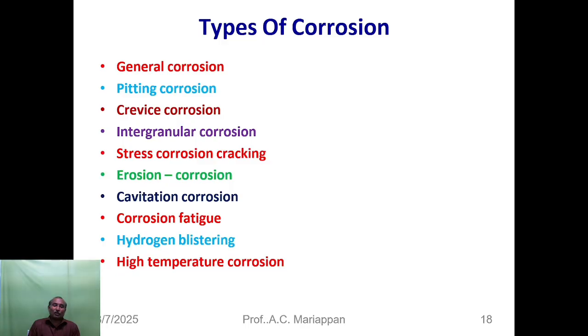The blister, the metal will be blistered inside the surface; it will not occur outside, it will occur inside of the equipment on the surface of the wall. By visual inspection, metal blistering can be observed. If you break the blisters, two nearby successive blisters are joined together by means of intergranular, the grain structure of the material joined together, that is the hydrogen. Main factor, entrapment of hydrogen. When hydrogen is entrapped inside the steel, then hydrogen blisters will occur.